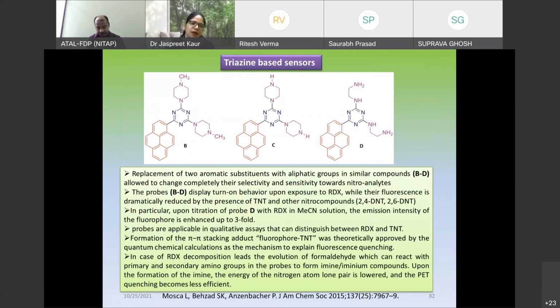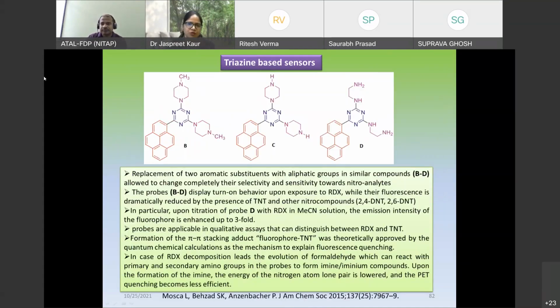These are other triazine based sensors. As compared to the previous one, in this case we have different substituents. If you look at these compounds, 2 of the aromatic substituents have been replaced with aliphatic groups, these ones over here. This replacement of the aromatic with the aliphatic shows a change in the selectivity and sensitivity for nitroaromatic compounds. If you look at this sensing probe B, it shows turn-on behavior for the detection of RDX, whereas the fluorescence is reduced in the presence of TNT. In particular, compared to D, it shows sensing performance for RDX in acetonitrile.